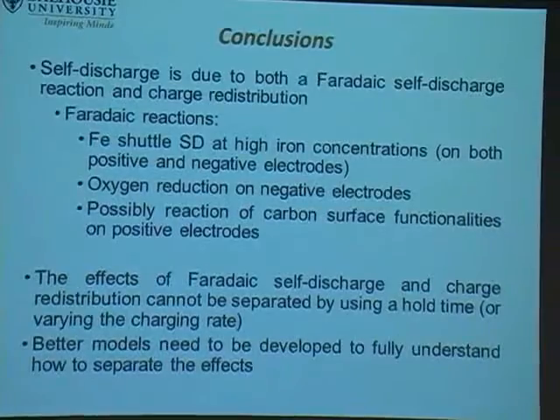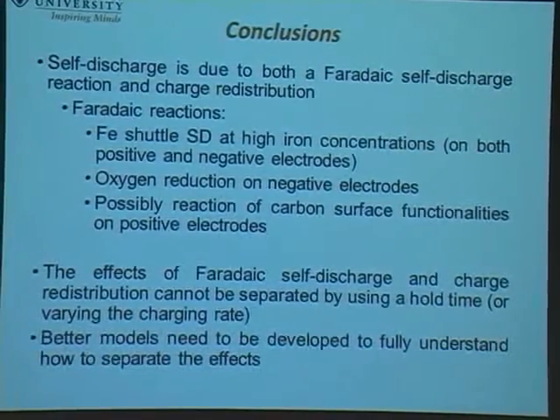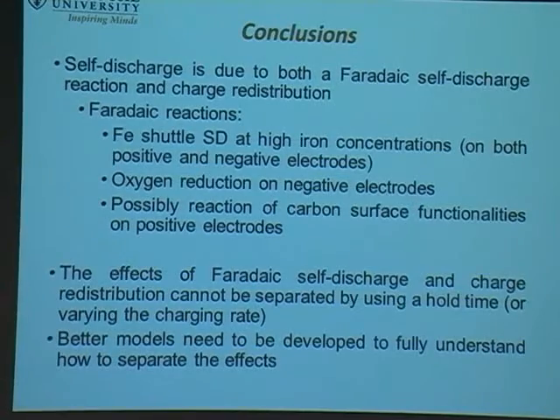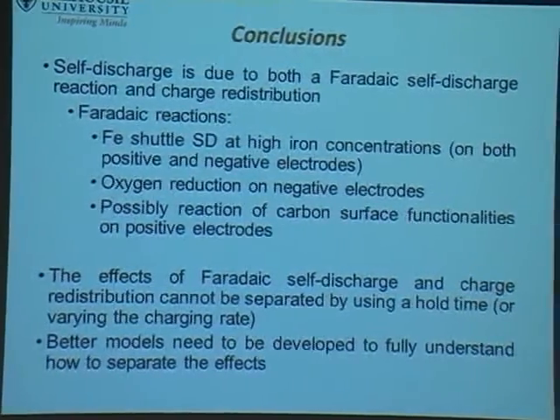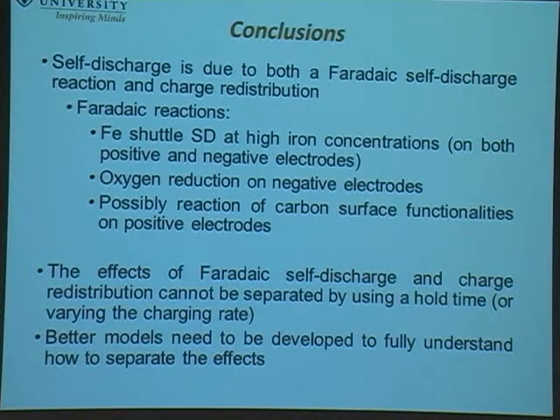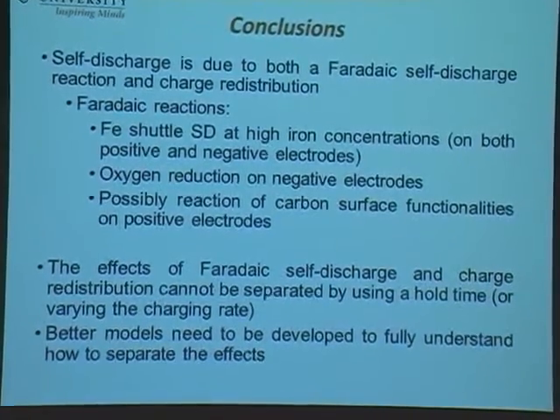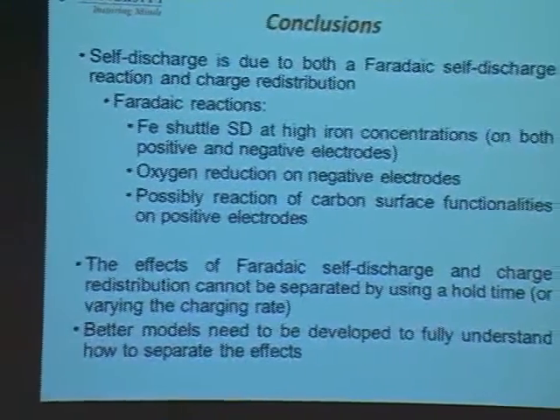And overall, these are the conclusions from everything I've talked about today. We've identified that charge redistribution and the Faradaic reaction are intricately linked, and it's really hard to separate them out. There are some tricks we can do in terms of looking at the slopes of self-discharge profiles, but in general, if you have a porous electrode, you absolutely have to consider charge redistribution as well. We've identified that iron shuttles are important at high concentrations, not really going to be super important in industry. They do play a small role, but there's something else that plays a bigger role. Oxygen reduction is absolutely important on the negative electrode. The surface functionalities, we believe, are the things that are causing problems in the industrial type setting.